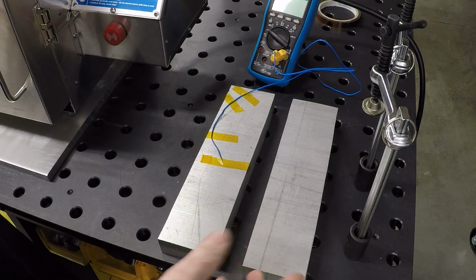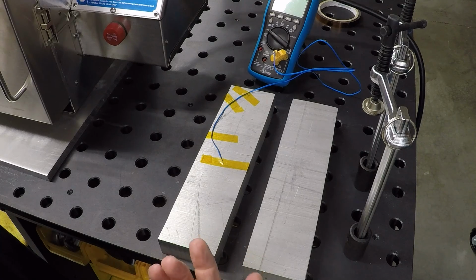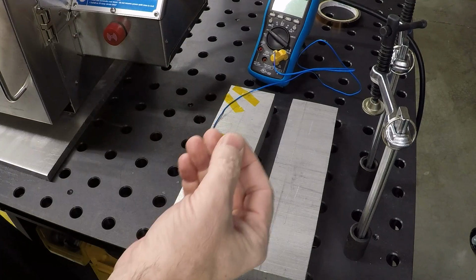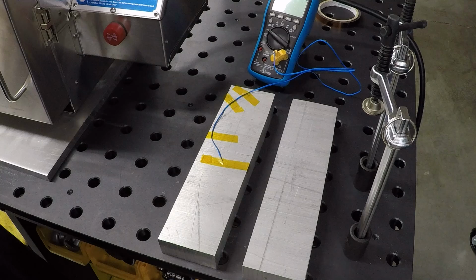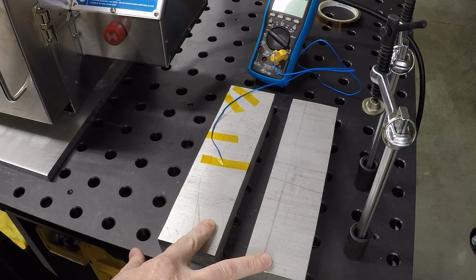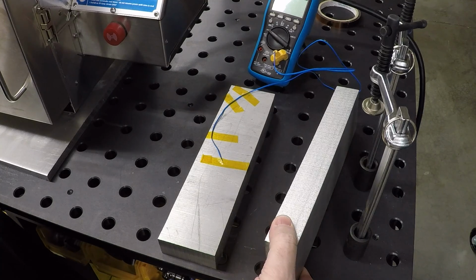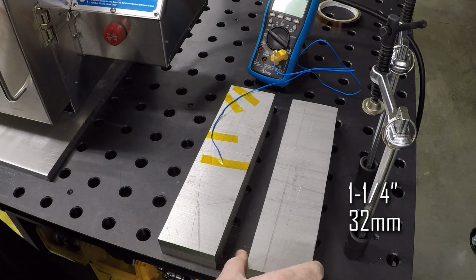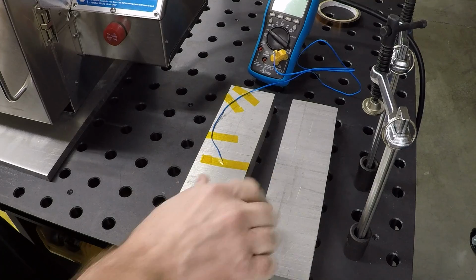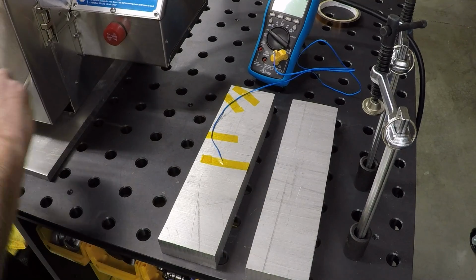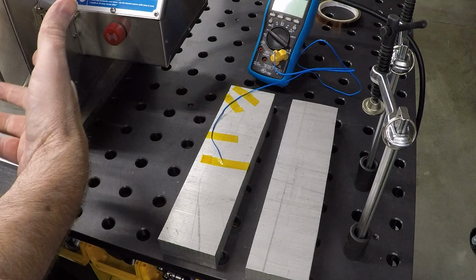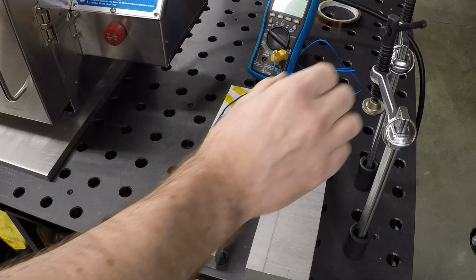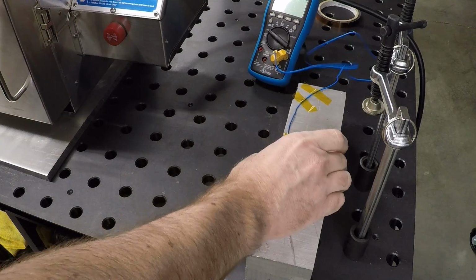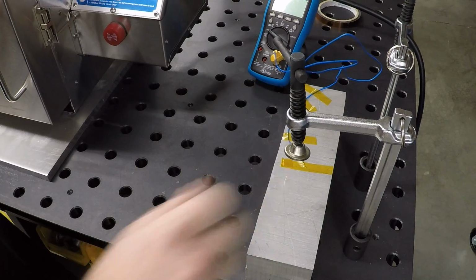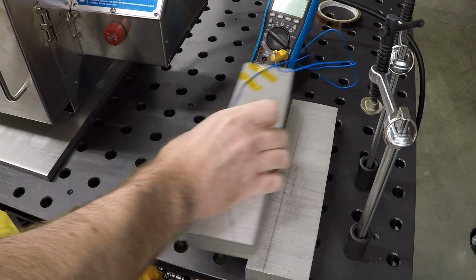Now D2 is an air quenching tool steel, so you can just pull it out and let it cool in still air and it will harden. But I'm going to use a technique called plate quenching. I've got a couple of pieces of aluminum. These are 1.25 inches thick. And so there's quite a lot of aluminum mass here, and I will pull the stainless steel foil packet out, still in the packet, set it here, set the other one on top, and clamp it down. And that will do two things.